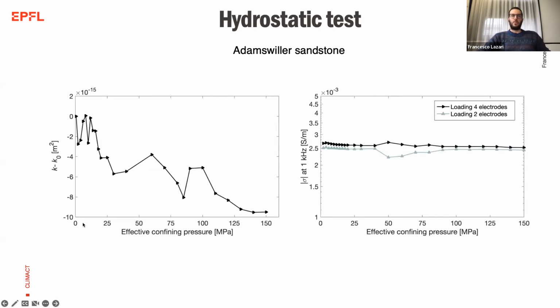In the first panel, we have the permeability variation with increasing pressure. We see that the permeability decreases a bit, not too much, but that's what we expect, because we are not actually crushing the rock. We are just loading it elastically. In the second panel, we have the measurement of electrical conductivity in both 2 and 4 electrode setup, and we can see that both the measurements are quite in agreement with each other. There's a bit of shift between the 2, but it can be explained by the resistance of the electrode with the rock. This is something that is well documented in the literature.